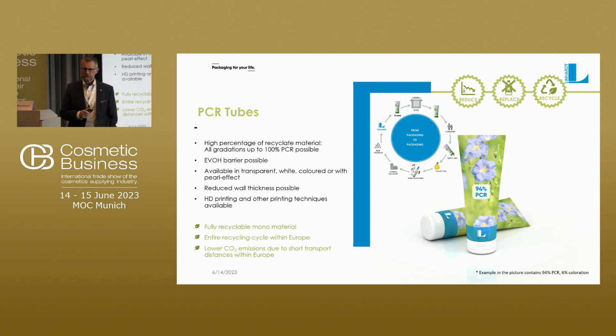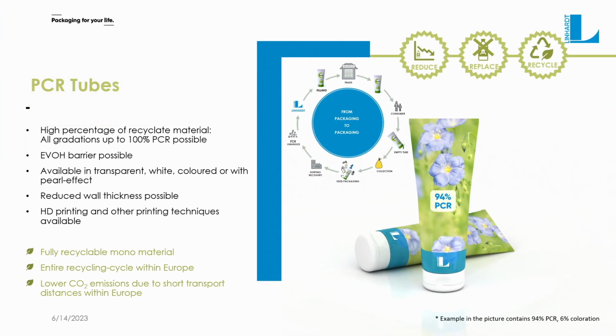Let me discuss the PCR tube. I told you about that earlier, and I told you that, generally speaking, from a technological point of view, we can actually offer a 100% PCR tube right now, but most possibly nobody will want it. That's because it's very rigid, very stiff. It has 100% PCR content, and you can also feel it in the tube. You feel inclusions of the recyclate in the material. And this is something you definitely want to avoid. What you need to try and do is try and find a good mix that will actually accommodate both needs.